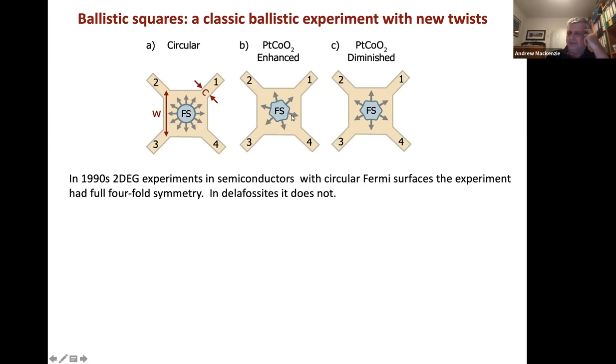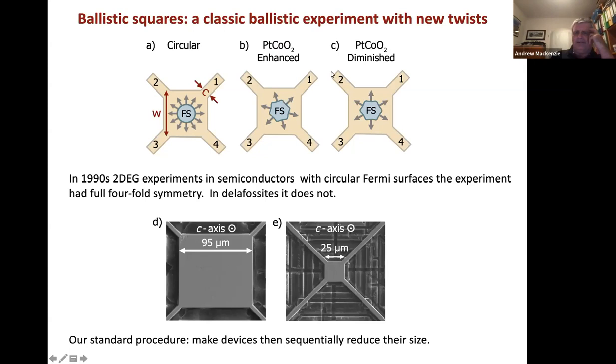And in fact, you can define two different ones, which we call, for reasons you'll see in a moment, the enhanced and the diminished orientation. So in the enhanced orientation, vitally, you have a mirror symmetry line going right the way through both of the diagonals. And in the diminished one, those mirror symmetry lines going along the diagonals don't exist. They've been swapped, rotated by 45 degrees to lie along the centers of the square, but longitudinally rather than diagonally. So we set out to see what this type of symmetry lowering would do in ballistic experiments.